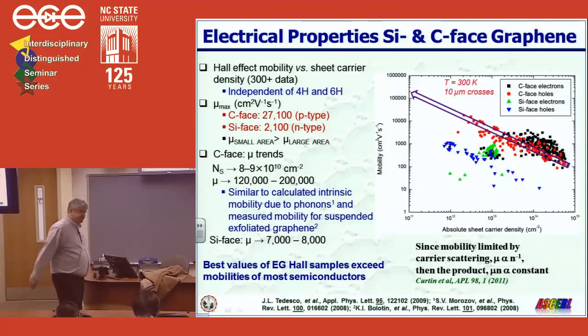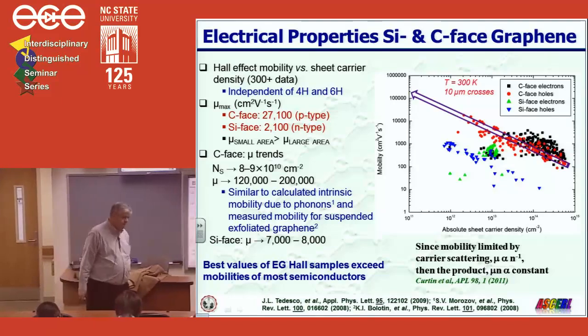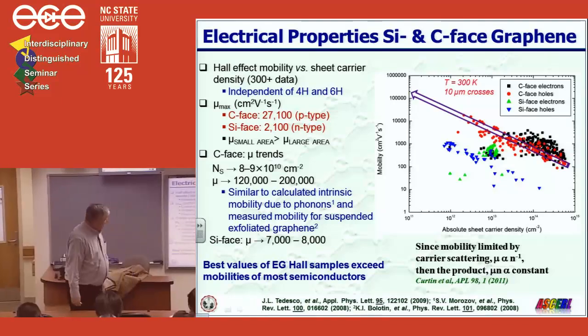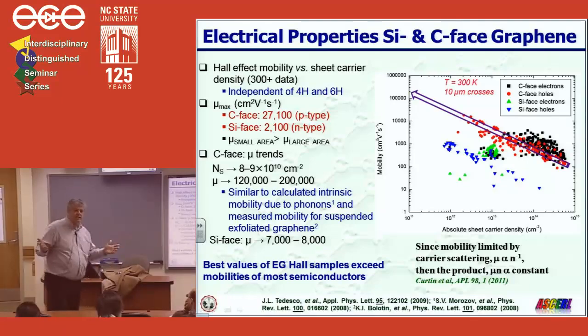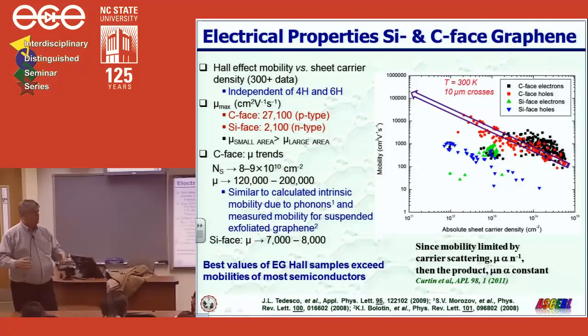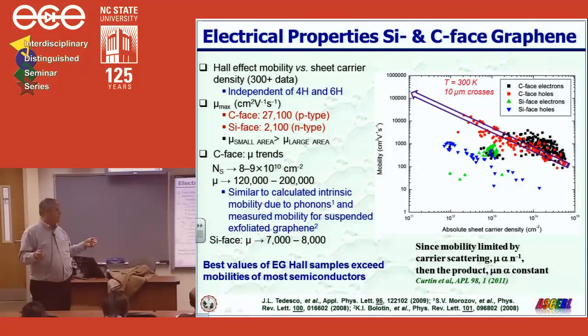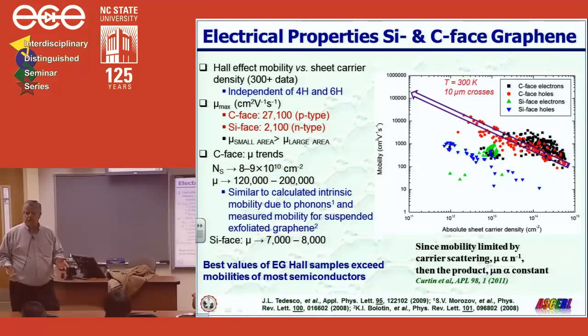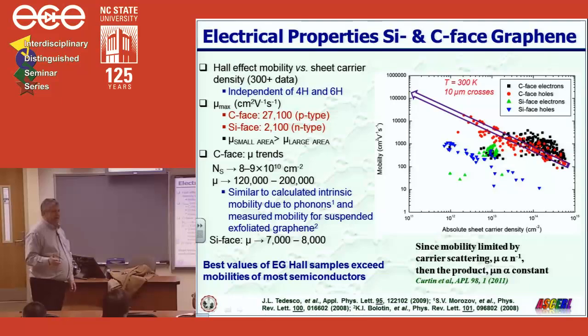Yes, sir? Is the sign of the carriers determined by Hall measurements different in those two cases? Yes, it is. And I'll tell you right now, there is a reason for all that. It's because graphene is all surface. It's like the thinnest piece of paper you can imagine. And so anything that adsorbs to the surface of graphene is a potential dopant. And it turns out that OH, water vapor, is a dopant, and it makes graphene p-type.